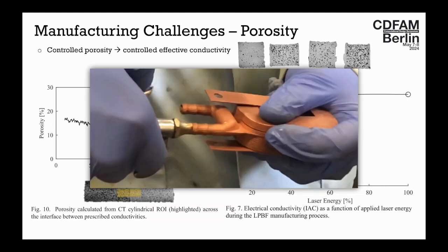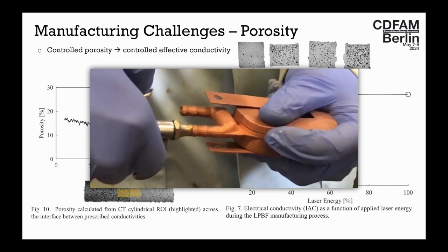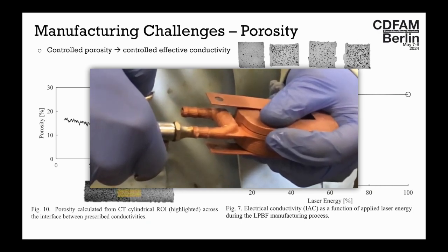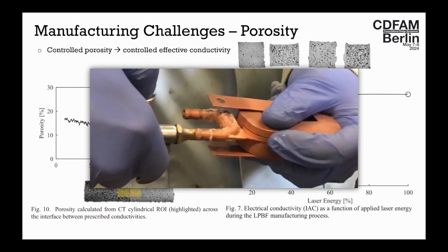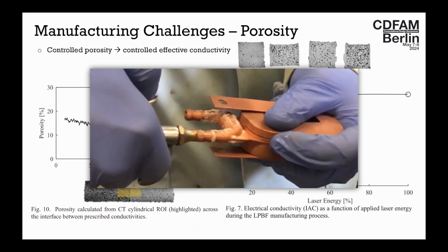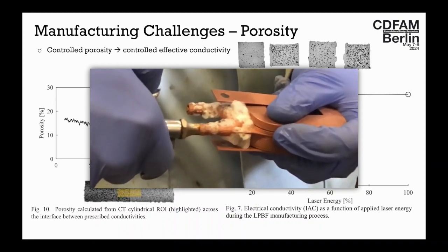The problem with porosity, when you're trying to design heat exchangers, however, is that if you don't very accurately dictate exactly where that porosity is supposed to be or not, you end up with a heat exchanger that's very, very leaky. So this is foam being blown out of the side of a heat exchanger. Up until this point, I had no idea that metal could be porous without visibly being porous.